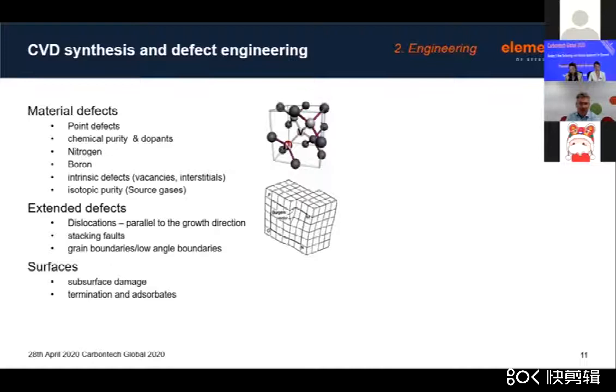So the control of those defects in the CVD process is again quite important to getting different properties of it. And then finally, you've got actually the template that you have for growth in single crystal diamond, and quite a lot of the properties of diamond can actually stem from that substrate that you've grown on.